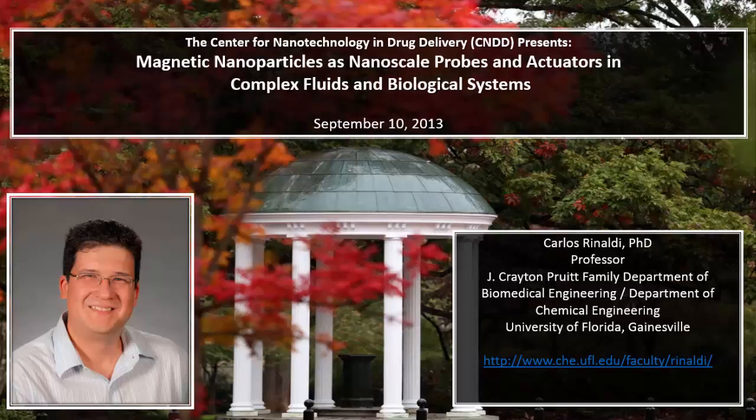If instead of doing the frequency measurements, we make measurements as a function of temperature, but at fixed frequencies, this is what we get. This is the in-phase component. This is the out-of-phase component. We start here with the gelatin completely melted, or dissociated, and then we lower temperature, and this is where we hit a transition where gelation is starting to happen. And we see a very sharp transition in the measurements, both in the in-phase and out-of-phase.